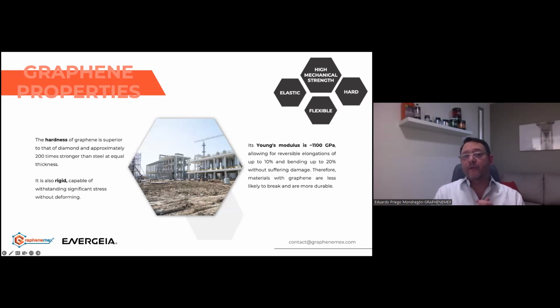The hardness of graphene is superior to that of a diamond and approximately 200 times stronger than steel at an equal thickness. It is also rigid. It's capable of withstanding significant stress without deforming. Its Young's modulus is 1,100 gigapascals, allowing for reversible elongations of up to 10% and bending of up to 20% without suffering damage. Therefore, materials with graphene are less likely to break and are more durable.